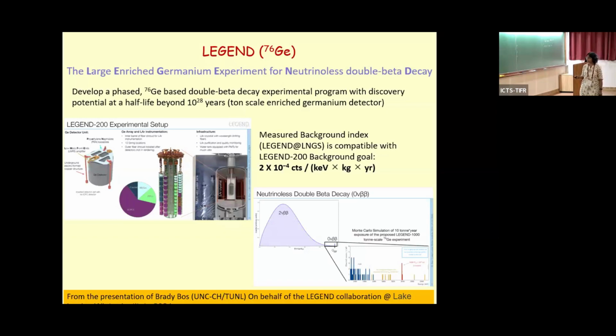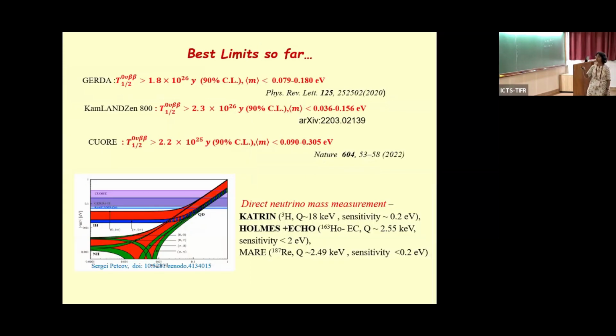And what do they expect? They would expect to see about 4 events. I think you can't read that, but about 4 events after running for 10 years. So that's the goal right now. But they have actually achieved the proposed goal of 10 to the minus 4 counts, so this is now 0.0002 counts per keV per kg per year. And that's where they expect to get a sensitivity of 10 power 28 years. So they should be able to hit the bottom of the inverted hierarchy.